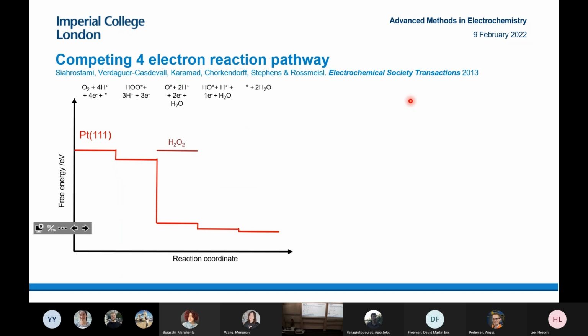But the problem, as I already mentioned, is that you have a more thermodynamically stable product, and that's water. This is the free energy diagram for platinum 111. I believe this is 0.9 volts, but I'm not sure, maybe 0.7 volts. This is the free energy of hydrogen peroxide. It's much more downhill to form oxygen and then make water. That's why you end up making water, not hydrogen peroxide, on platinum 111.